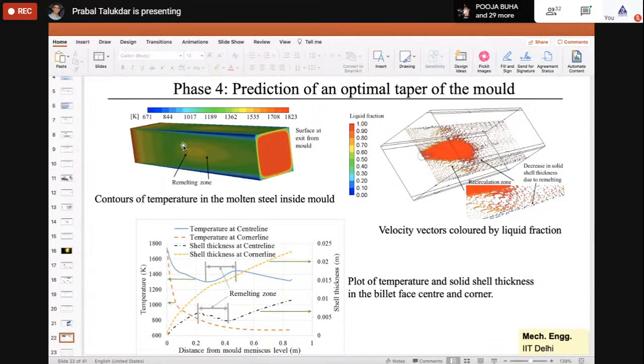One phenomenon we have observed here is that there is a remelting zone which happens somewhere in the middle of the mold, because you can see the jet comes down at a high speed. It starts solidifying from the top at the meniscus, but because of this high jet, it strikes the boundary of the mold, and because of that flow, the solidified shell is remelted here and becomes liquid again. In this diagram you can also see this blue color. This is the shell thickness.